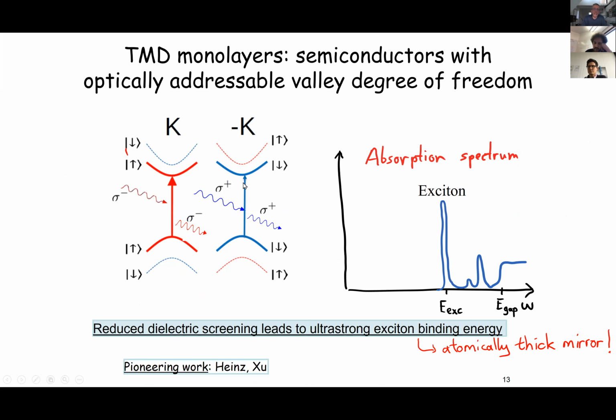And indeed, this is the case, and this is what makes the system interesting from an optical perspective, because the band gap is on the order of 1.5 to 2 electron volts, which makes it a perfect match for, say, investigation with optical techniques and Ti:sapphire-based lasers. Now, there are interesting properties here.